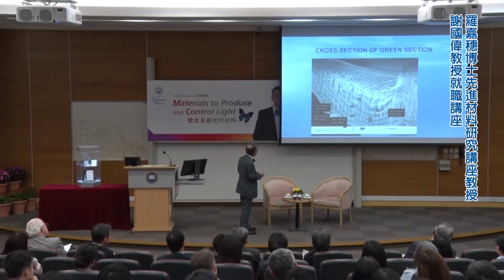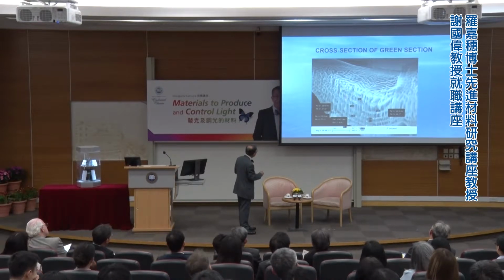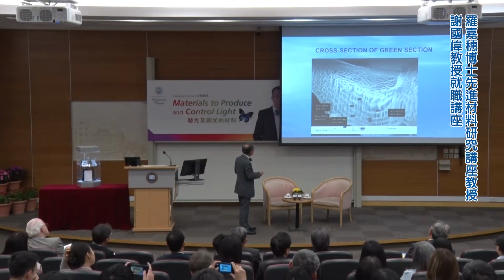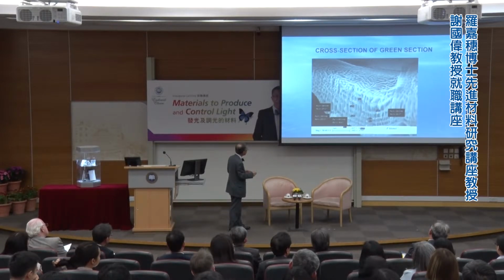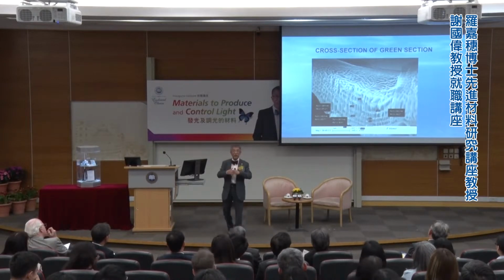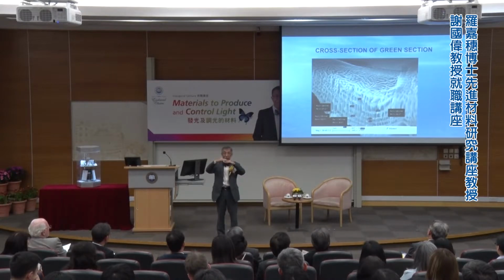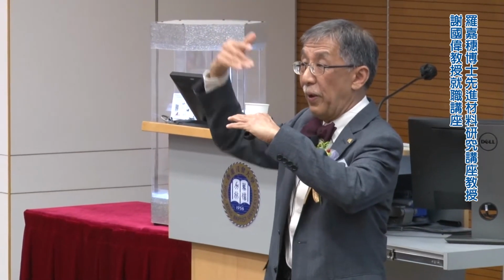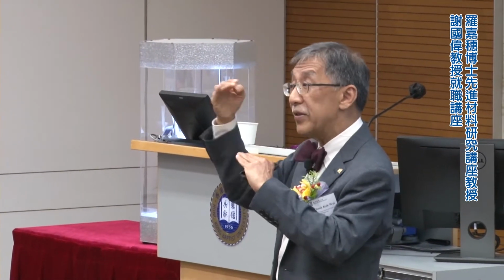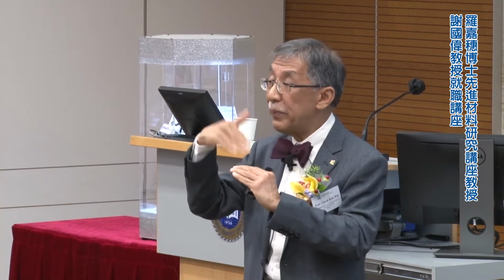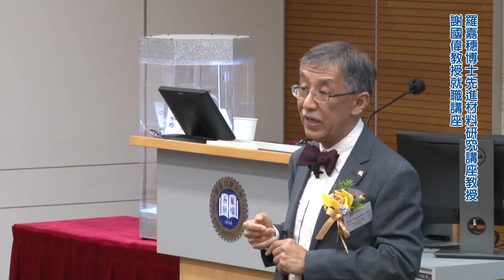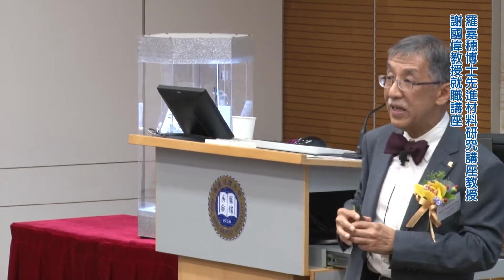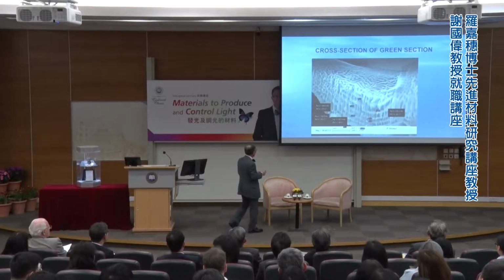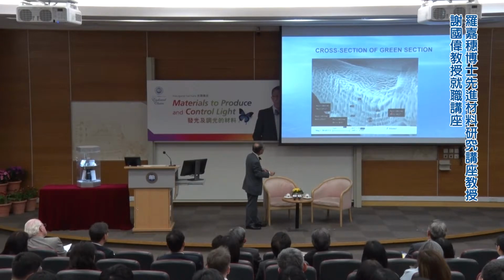And you can count the layers. You can see a little bit of melting. Then we count the structure. So basically what we see is that this is solid, and then we have empty space in the middle. In physics we'd say you have one solid material, then air, solid material and air. So you have two different materials, air and solid material. That gives you what we call a one-dimensional reflecting layer, what we call Bragg reflectors. And that's amazing. What we are looking at here is 100 to 300 nanometers.